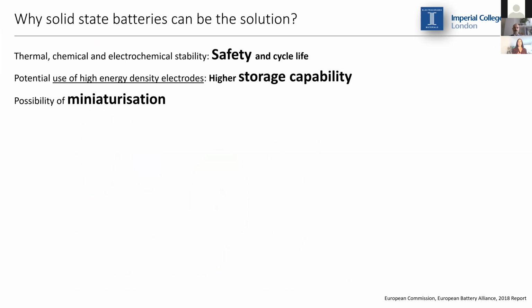The second one is that if we have a good electrochemical stability window in the electrolyte, we can also use high energy density electrodes, and therefore increase very much the energy density and the power density of the systems. Also, there is the possibility of miniaturization. But one of the most important things of using a solid electrolyte is that it could allow us to substitute the graphite that we're using as an anode nowadays by lithium metal, which has 10 times more capacity.